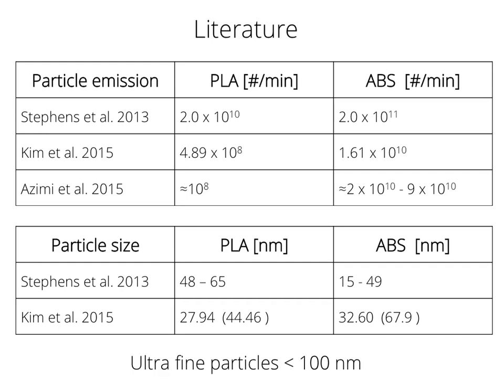Kim et al. in 2015 also investigated particle size. The number in the bracket is the geometric mean particle size before they started printing, so it was 45 nanometers before they started printing, and during the printing process the particle size geometric mean was 28. This means Kim et al. had lower particle sizes being emitted by PLA than Stephens et al. had in 2013. For ABS, Kim et al. 2015 had 33 nanometers as a geometric mean, meaning this would actually fit quite well into the particle size range from Stephens et al. 2013.